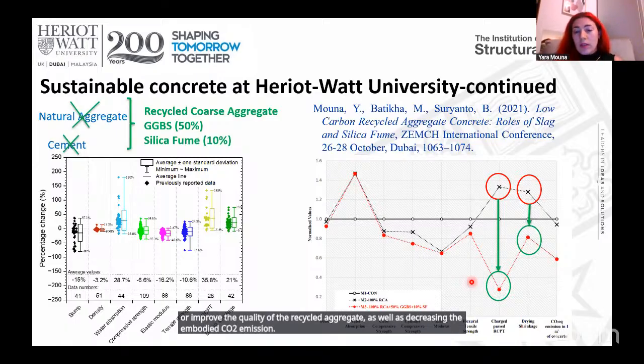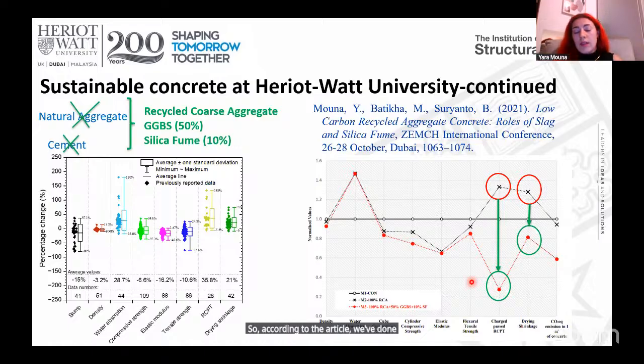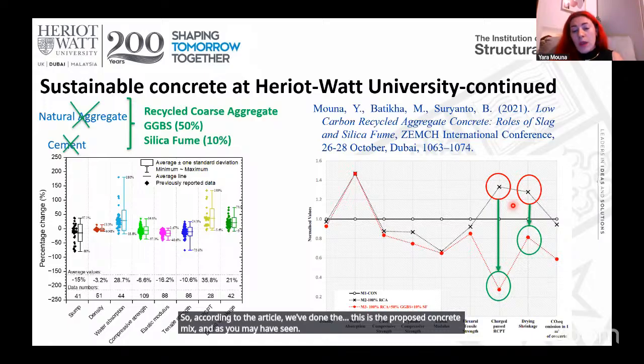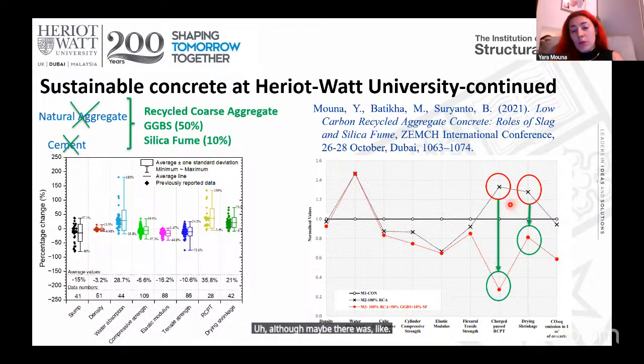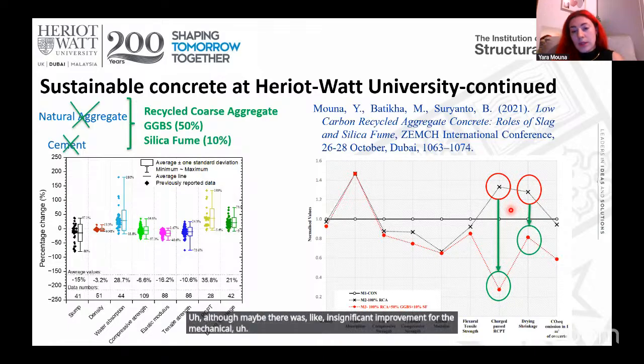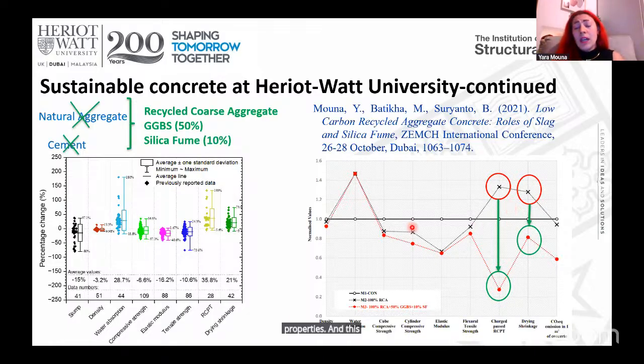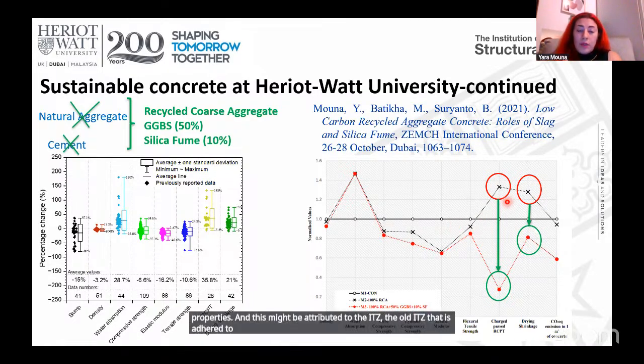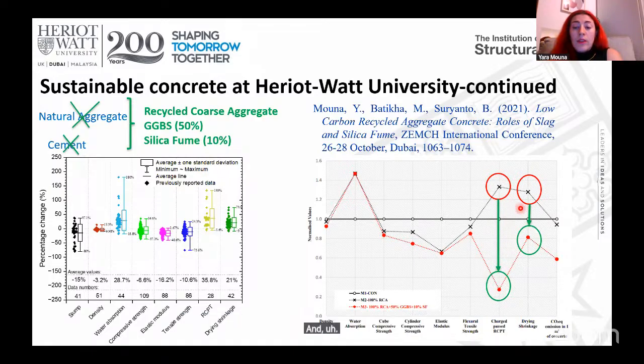So according to the article we've done, this is the proposed concrete mix. As you may see, there was an insignificant improvement for the mechanical properties, and this might be attributed to the old ITZ that is adhered to the mortar of the recycled coarse aggregate. But interestingly, there was a big improvement in the durability properties: the chloride ingress dropped about 80%, while the drying shrinkage dropped about 35%.